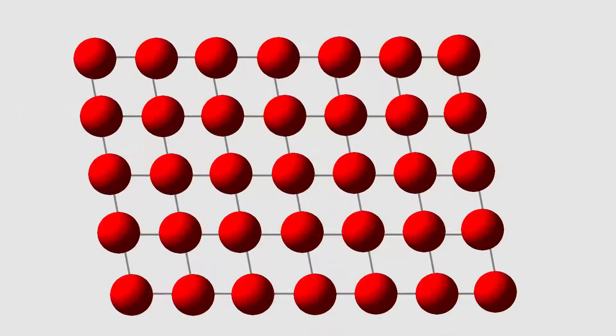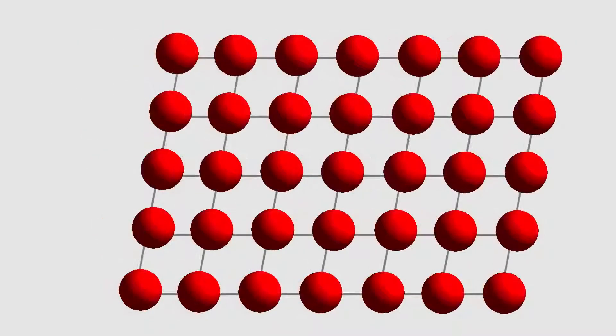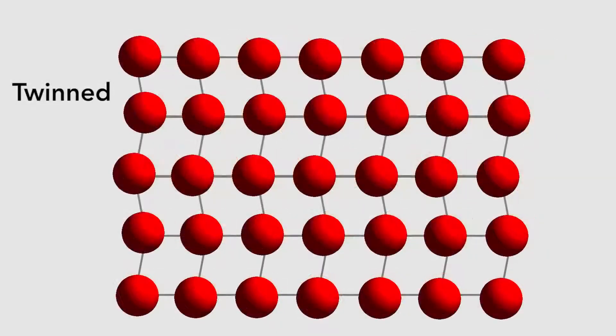You could have all of the rhombuses oriented this way, or this way. And as you can now see, when the nitinol cools, it forms equal amounts of these two orientations of rhombuses. One's oriented this way, and one's this way.